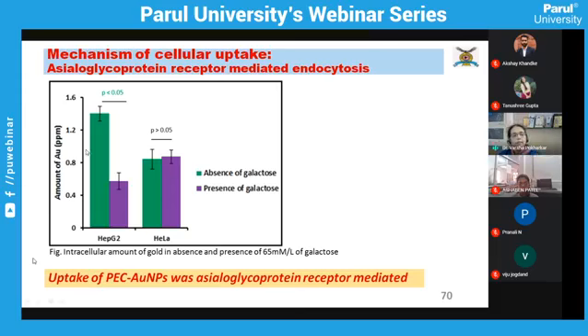So this is again just the comparison between the HEPG2 and the HeLa. Here you can see in the absence of galactose, there is considerable uptake. But when you add galactose, galactose is going to compete with the pectin for the receptor. And selectively, obviously, the galactose will saturate the surface. That is why the amount of gold nanoparticle uptake is going to be reduced. Whereas in case of the HeLa cell line, which is asialoglycoprotein negative, absence or presence of galactose does not matter on the uptake of the gold.